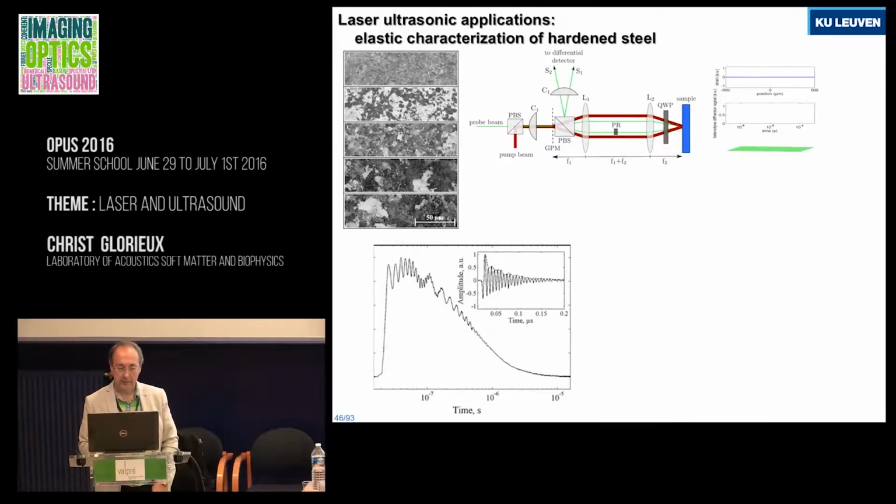The size of the grain also determines the amount of scattering of the acoustic waves. Grain sizes are of the order of micrometers. Acoustic waves at high enough frequencies will scatter. You will have Rayleigh scattering if the acoustic wavelength is much longer than the grains, and you will have other kinds of diffusion even when the grain is as large as the wavelength of the acoustic wave. If you play with the wavelength, as we can do by changing the crossing of the laser beams, we can do a kind of spectroscopy of the scattering.